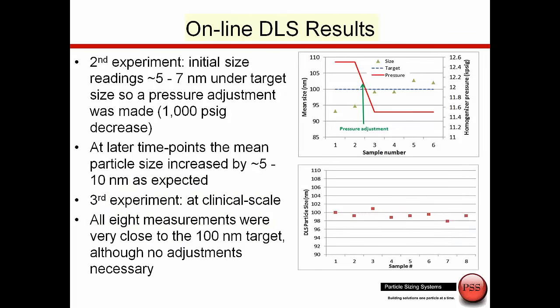Now we understand the measurement time and what changes in pressure are required to tune to the desired particle size. In this batch we took about six samples. At the start these particles were a bit too small, down in the range of about 92 nanometers, so we lowered the homogenizer pressure and tweaked it to very close to the magic 100 nanometer size range. Here we've got a feel for tweaking the process, looking at the size, and controlling it.